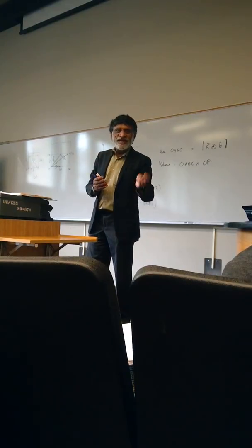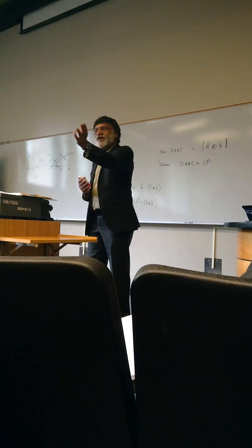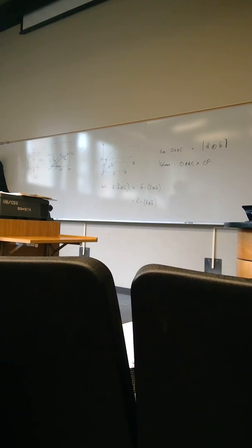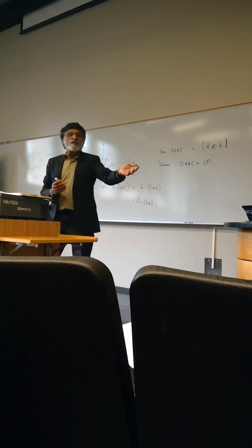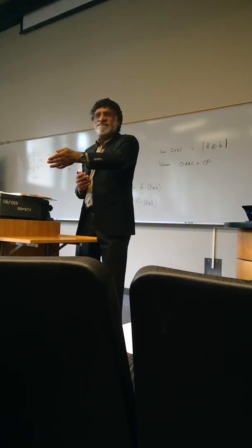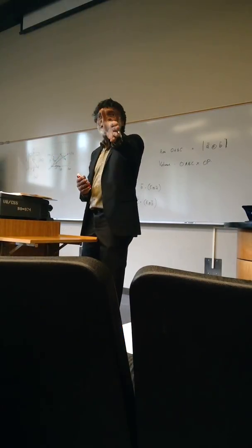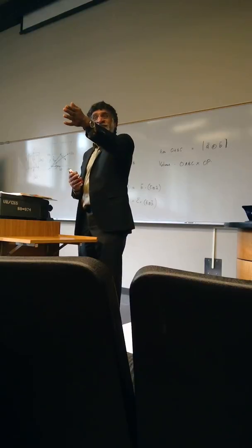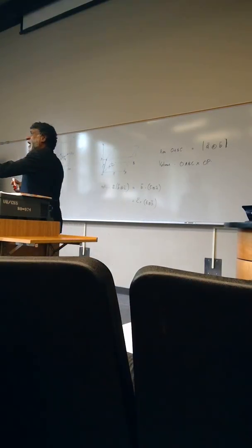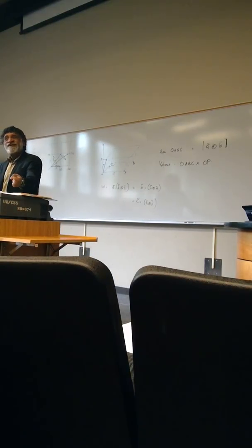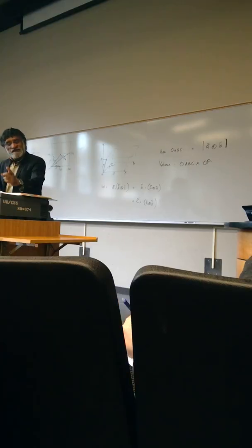Take a guess. It's a very easy guess. If you take a reciprocal of the FCC lattice, there's only another cubic system that you will get. It has to be cubic, yes? That much by symmetry. You get a BCC. Take the reciprocal of the BCC lattice, what will you get? FCC. That's a very interesting thing.